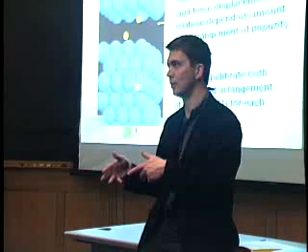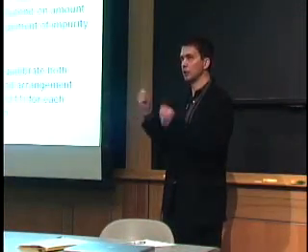And so this is actually why it's so hard to include chemistry in mechanical calculations, because you're really working on two different time scales that are very hard to combine. And so the solution here was essentially to calculate the relevant free energy of hydrogen for any state of crack opening. For any state of separation of the planes, you try to get the equilibrium hydrogen content by a cluster expansion. And then from that envelope of free energies, you get the force.